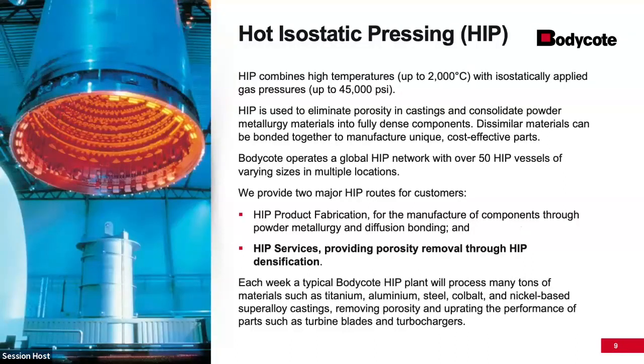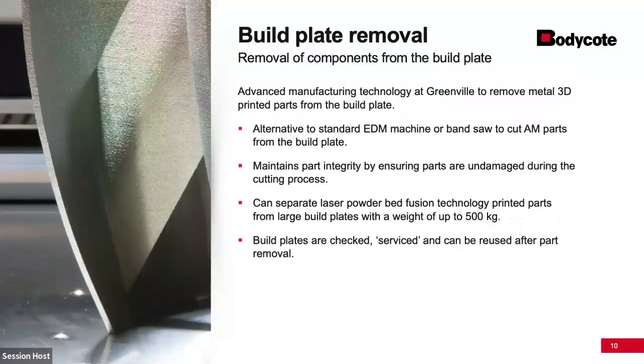So build plate removal and other value add. The parts are generally built up on a plate, and we have an alternative to standard EDM machine or bandsaw to cut the parts from the build plate. You maintain part integrity by ensuring the parts are undamaged during the cutting process. You can separate laser powder bed fusion parts from large build plates up to 500 kilograms. The typical build plate when additive came out was about 350 millimeters. They've grown significantly over time, and build plates are checked, serviced, and can be used again and again up until you exceed your part thickness of the build plate.